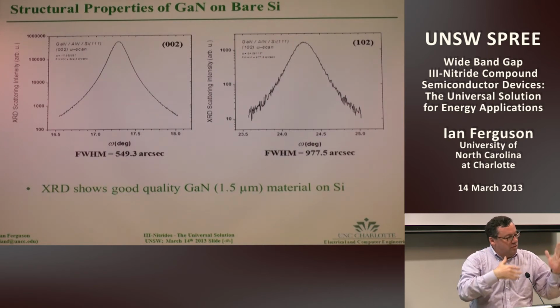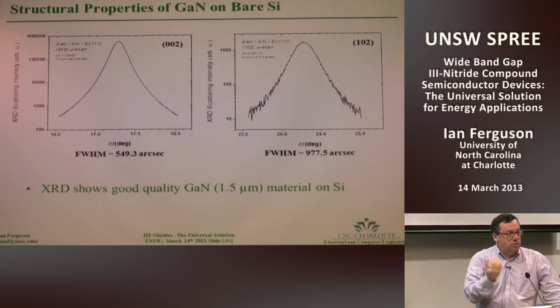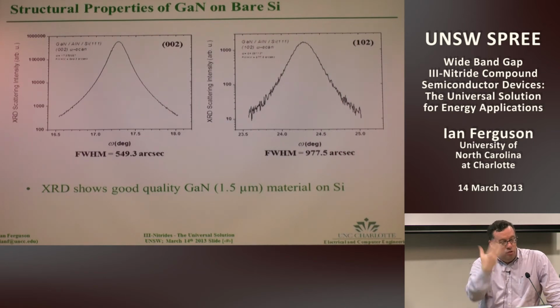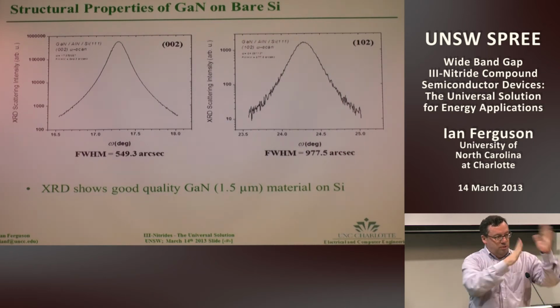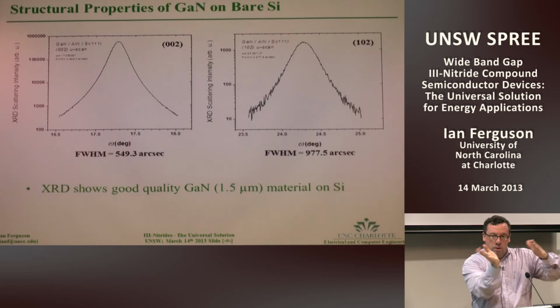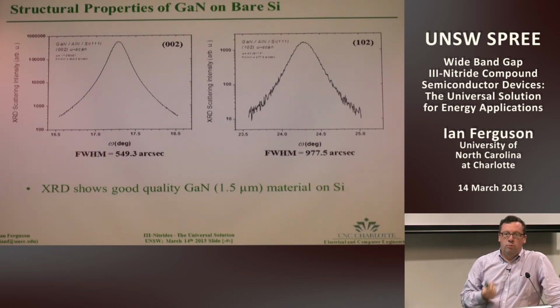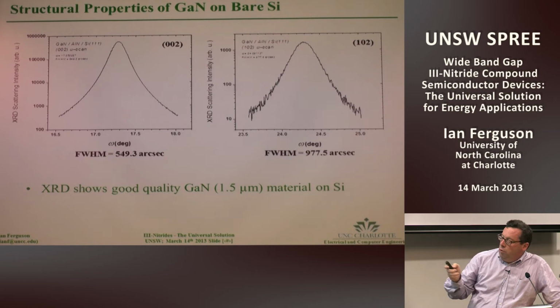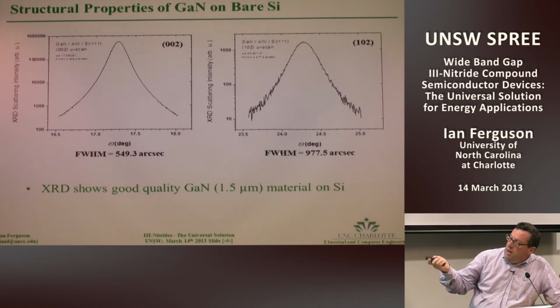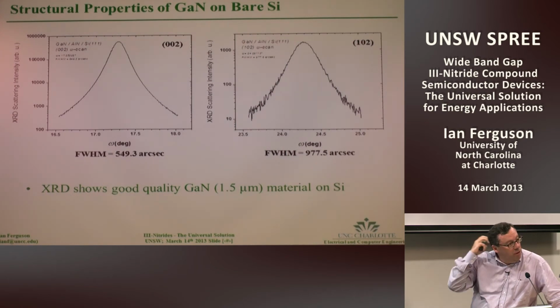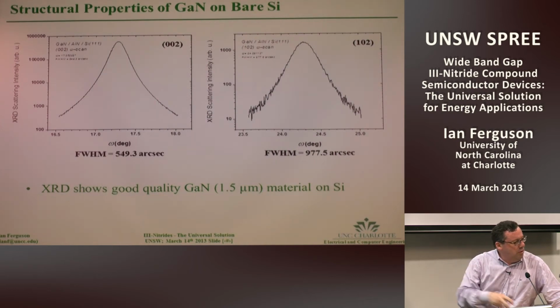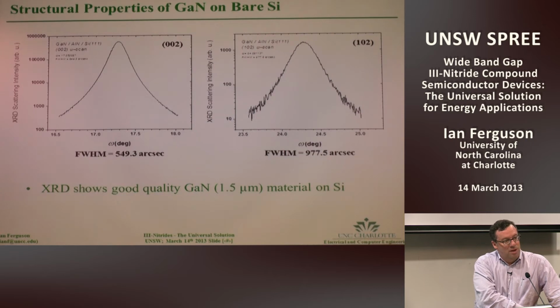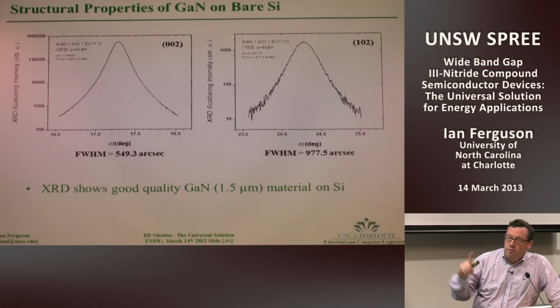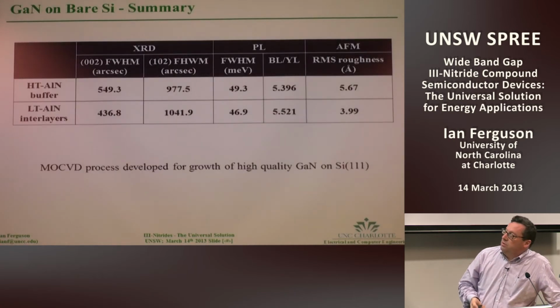The other parts, the screw-type dislocations, will typically self-annihilate as you grow the material out, but the edge-type dislocations will tend to run somewhat parallel to each other, so they're more problematic to remove. The other thing is, if you don't pull this down to around 400 or so, it becomes very hard to actually p-type dope these materials, and one of the issues with the wide band gap materials as a whole was making good PN junctions. There are other issues when I come to talk about solar cells in a moment as well.